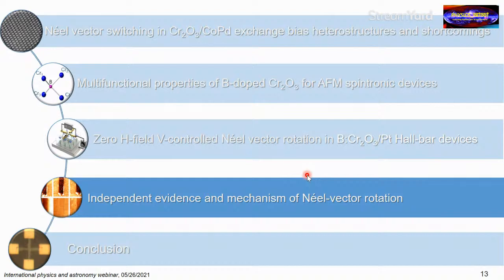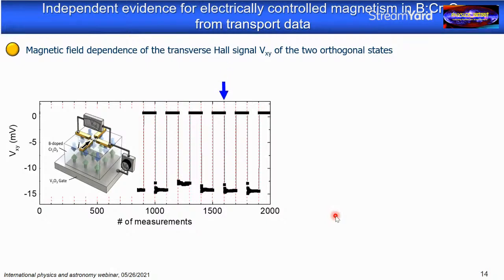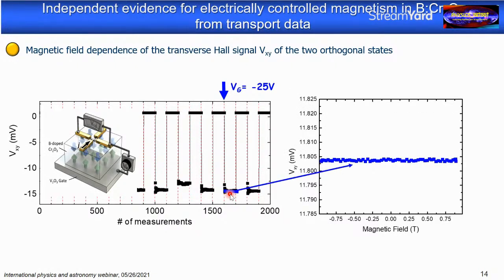But it's a big claim also, and the big claim requires an independent confirmation, and that's what we did here. So we want to make sure that the signal we see, and in particular the switching, is indeed a switching between different magnetic states. And the first thing we could do in our group was to look, is the behavior on a magnetic field different in this state compared to this state? So if we switch from this state into a state of non-zero Hall voltage, and we investigate the magnetic field dependence, then we get the result that virtually is none. The voltage versus magnetic field is almost flat. Very similar to pure chromia. When the pure chromia is far below its Néel temperature, it's also little to no reaction on the applied magnetic field.